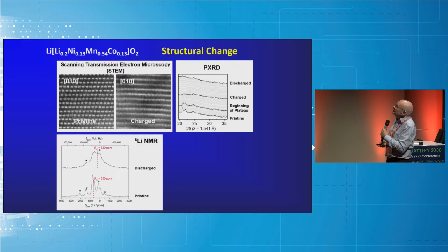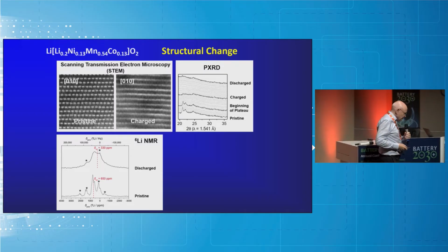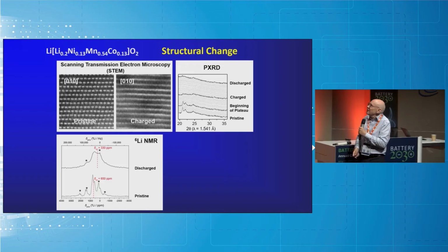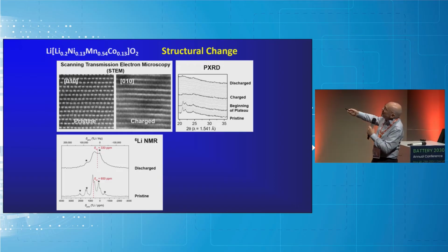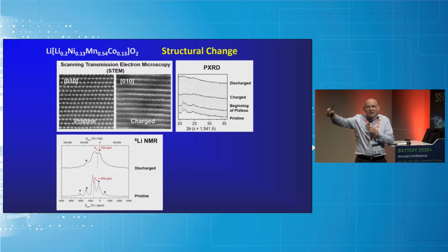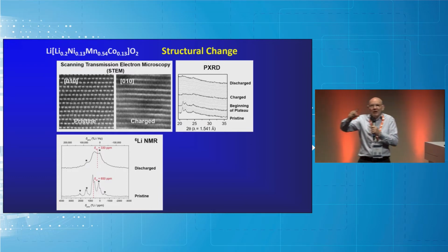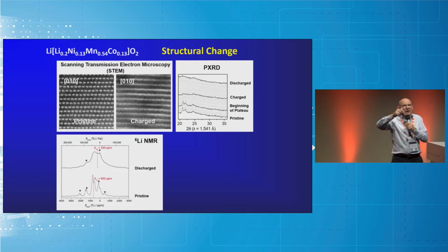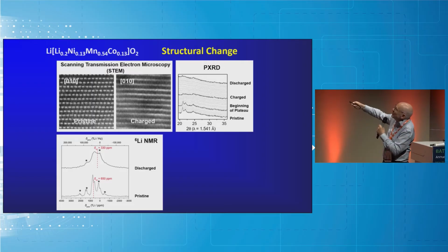So if we now take some STEM images of our material, so again, now we're looking along the layers, scanning transmission electron microscopy. This is the pristine material before we do any charging. And remember, in electron microscopy, the light dots are the heavy elements from the scattering of the heavy elements. So a line along there of those dumbbells represents the transition metal layer, and those dumbbells, those sort of pairs of dots, are exactly what you expect for that honeycomb structure. So it's exactly what we anticipate from our known honeycomb structure.